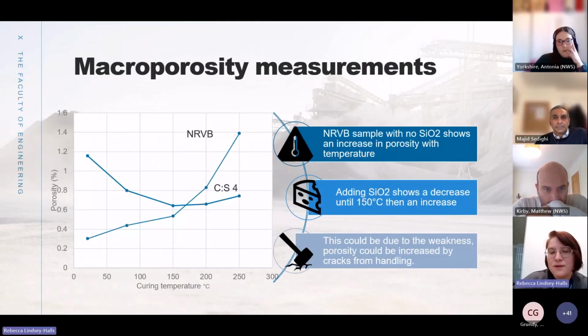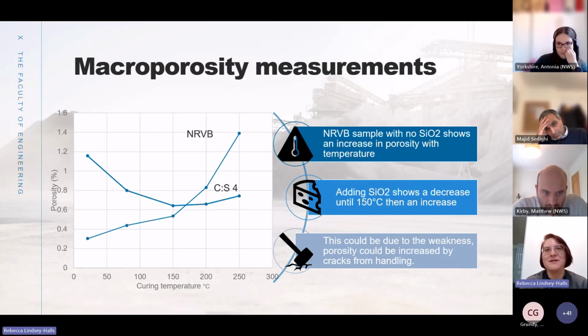So this is macroporosity from the XCT scanning. I'm just going to mention, I've also looked at the microporosity, which is about 40 to 50%, which is what's seen in papers and industry. But the macroporosity is from scanning, so it's quite impacted by the resolution you can get. So if you're not getting a particularly great resolution where you can look at tiny micrometer measurements, you're just going to see the larger pores.